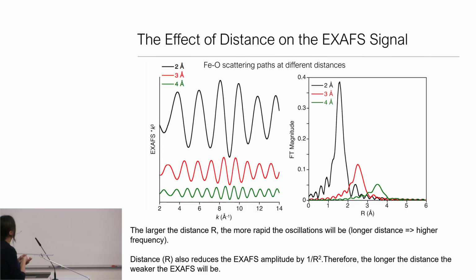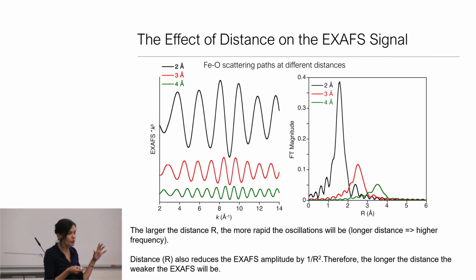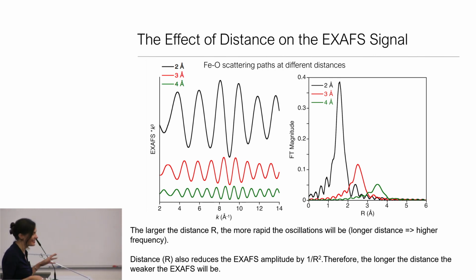Here I'm just showing you FEFF calculated. FEFF is kind of the go-to program in the XAFS community. You'll hear about a lot of different programs like Larch and Artemis, but most of them actually interface to FEFF underneath. So FEFF is probably the internationally most used XAFS code. With that code, I just calculated iron-oxygen scattering paths at 2 angstroms, 3 angstroms, and 4 angstroms.